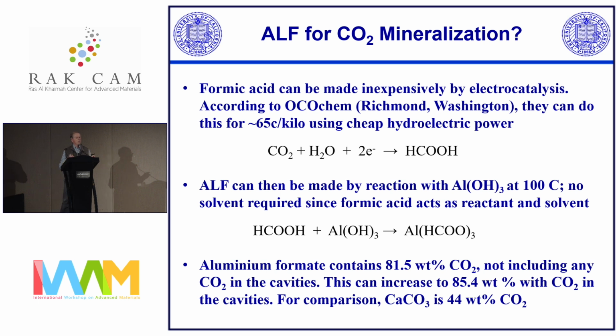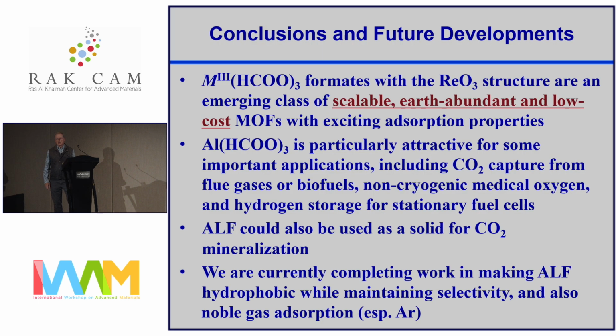And if you calculate what's the weight of CO2 in the framework of ALF, it's 81%. So this is not adsorbed CO2, this is CO2 that's wrapped up in the framework as the formic acid group. And so if you add in the CO2 you could put in the cavities, it goes up to 85 weight%. And for comparison, calcium carbonate's 44 weight% CO2. So there's a big advantage in having aluminum because it's so light. And then if you look at MOFs storing in the cavities, then the absolute maximum absorption is about 27 weight%. So this is a really interesting option for CO2 mineralization.